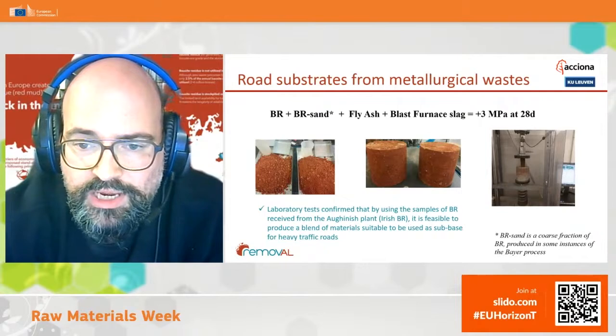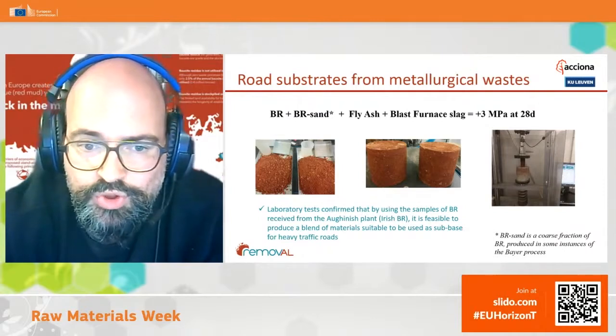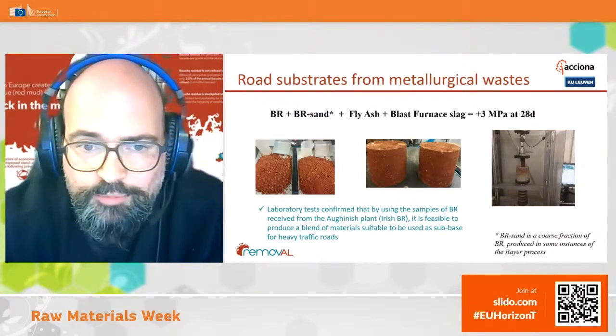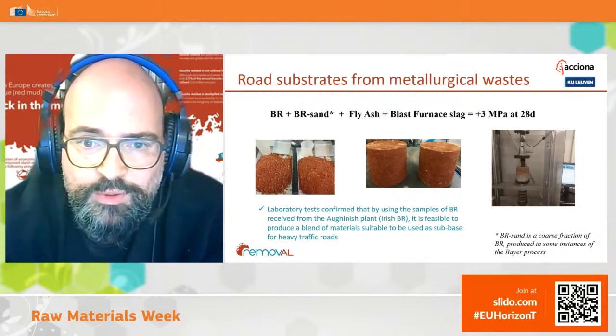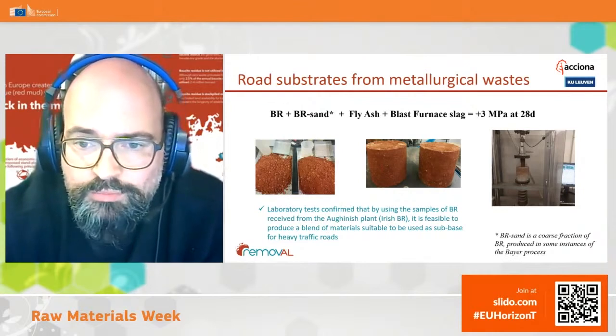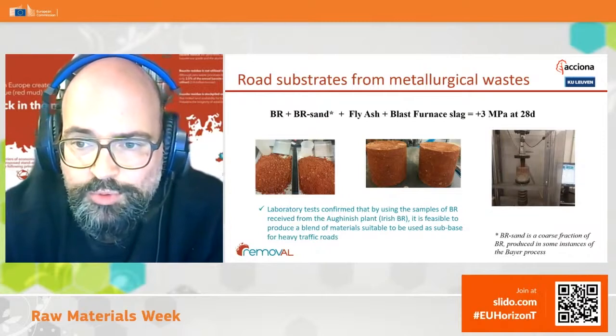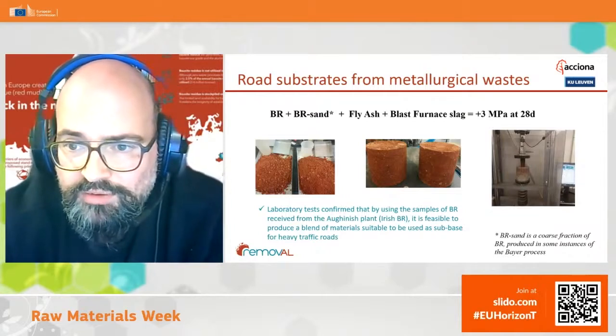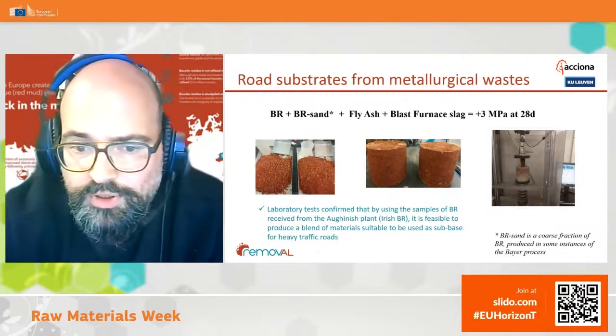Here the technology can be summed up in this simple equation. You take bauxite residue and bauxite residue sand, which is a coarser type of bauxite residue produced in some refineries, and now you add some more byproducts like fly ash and blast furnace slag. You mix them all together, and at 28 days you have 3 megapascal of strength. Next slide.